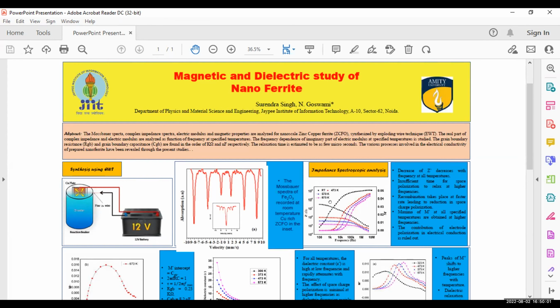Then we took the log plot of the AC conductivity versus log of the frequency at 2 temperatures. We got a linear graph, and from here the value of n, the power n from the Jonscher empirical formula relation. Through the literature we have strong evidence that if the value of n is less than 1, then hopping conduction is confirmed. In both cases the values of n are found to be 0.39, and in the other one it is 0.81 at room temperature. At both temperatures it was less than 1, and so hopping conduction is confirmed.